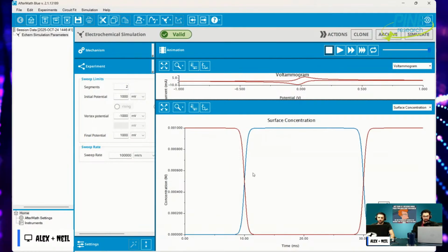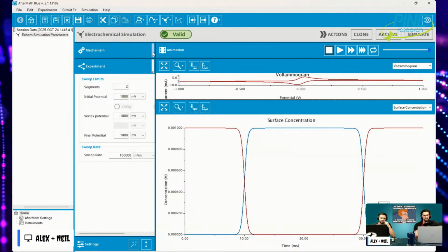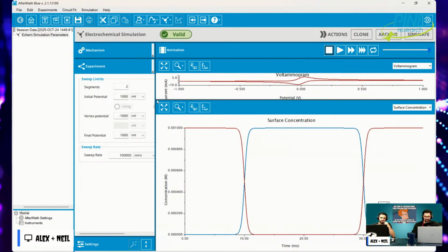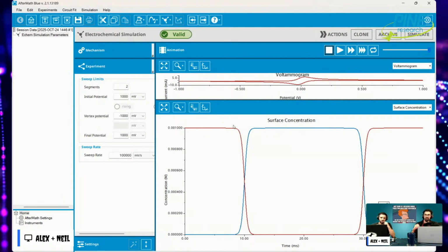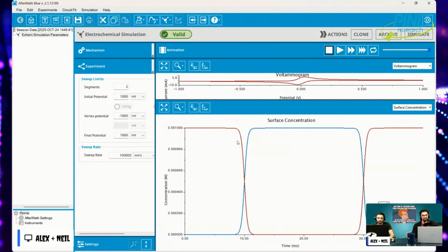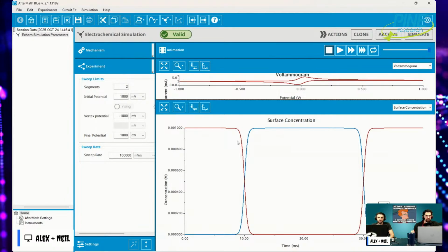And so this always has to happen, again with the Butler-Volmer equation, if the kinetics are sufficiently fast. I have a situation where the kinetics are sufficiently fast, so the system becomes Nernstian. We are at a potential where the ratio of oxidized and reduced species must be a certain way. It's got to be 10 to 1, 100 to 1, 1,000 to 1. It's got to be that way if the kinetics are fast, when you reach a potential.